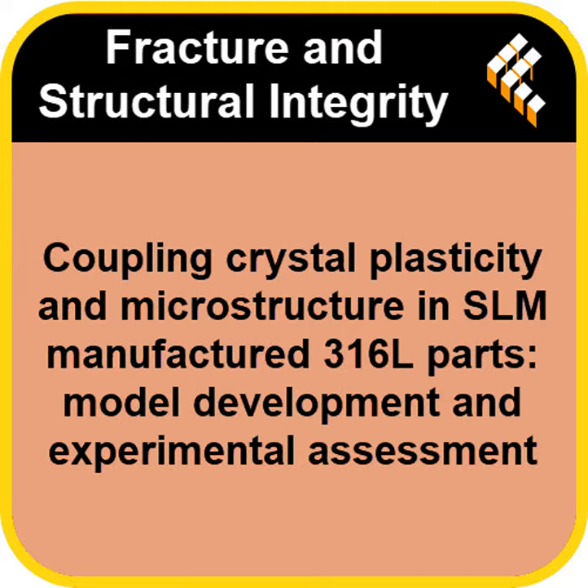Okay, that makes sense for manufacturing. So how does this statistical model actually turn those physical features, the 120 micron grains and the 0.3 micron twins, into numbers? It goes back to some fundamental materials science, specifically the Hall-Petch law. The Hall-Petch relationship basically says that a material's strength is inversely related to the square root of the distance a dislocation can travel before it hits a barrier. So smaller distance between barriers equals a stronger material. Exactly. And this is where the two classifications, soft and rigid, become so important for the model.